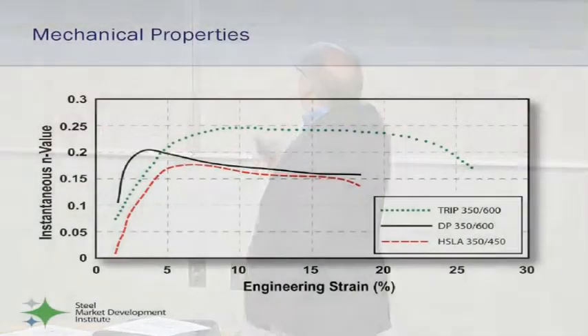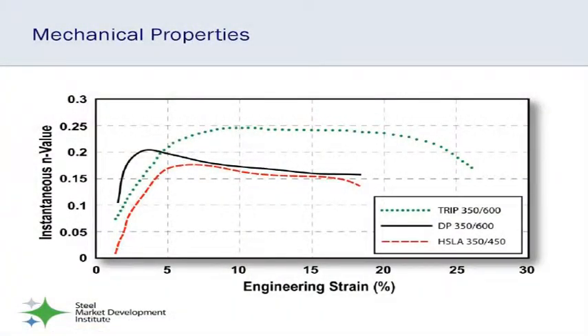What's that do for you? I talked about the fact that you get some great properties with steel. So you can see it's very formable. The TRIP steels, the dual phase, and the high strength low alloy are very formable. If you put the strain in it, you can see that it goes a very long time, up to 20, 25, 30% without ultimate fracture. And that's what the OEMs, the Detroit and international OEMs, really enjoy.